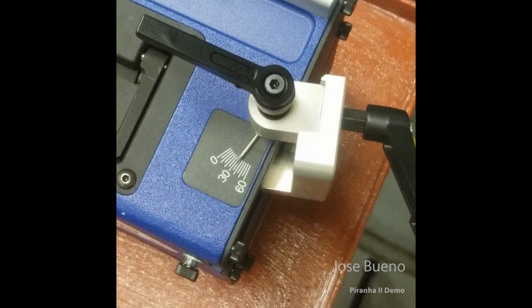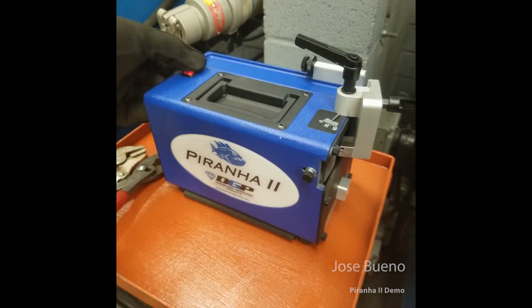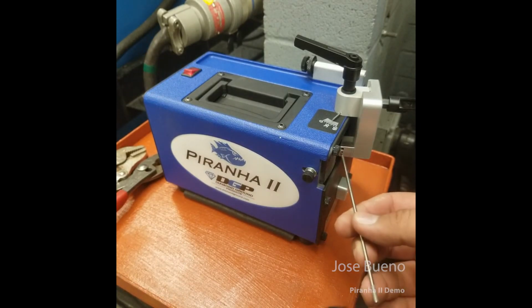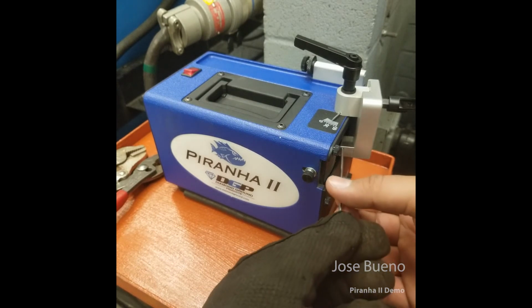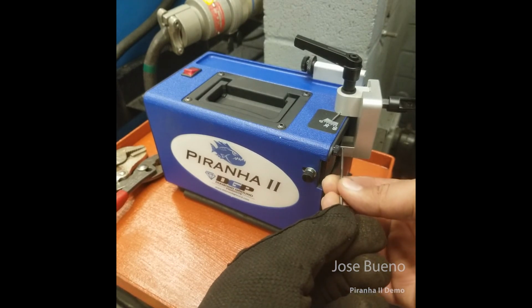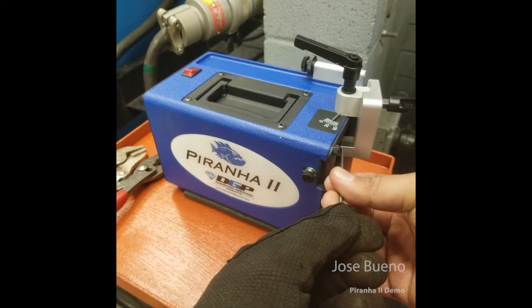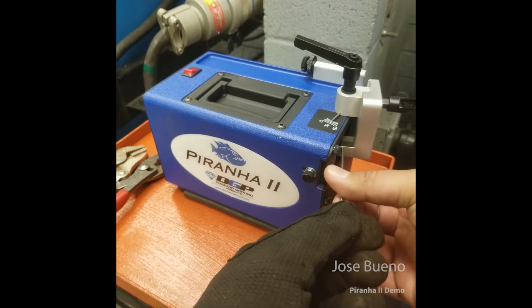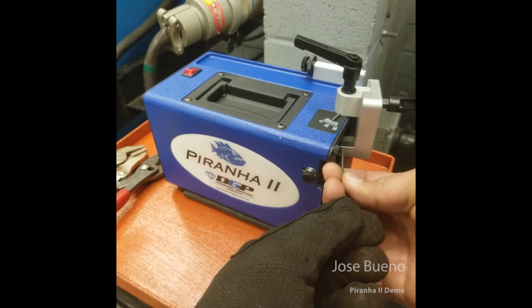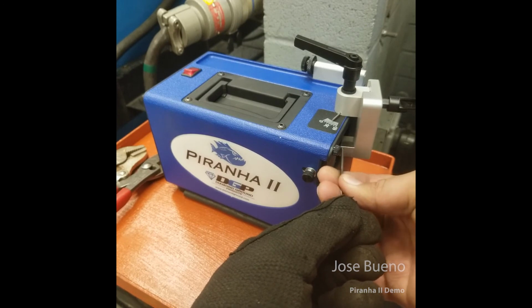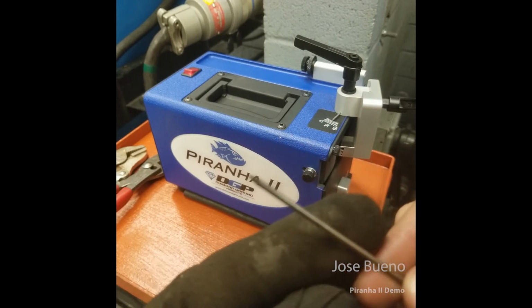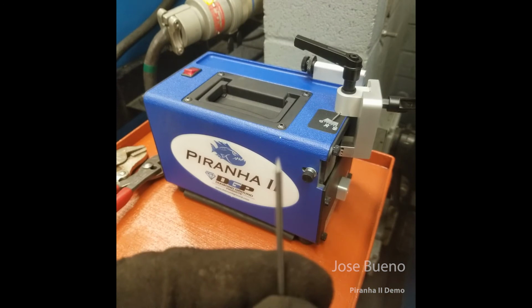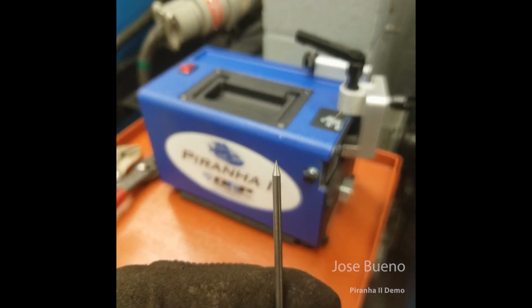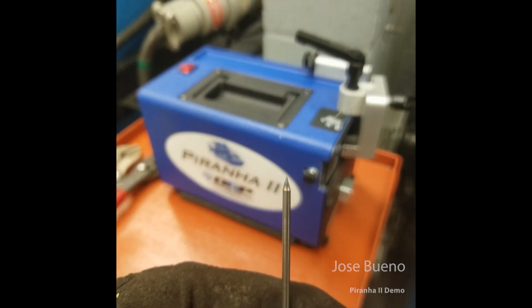And when you're ready to grind, just go ahead and switch it on. Allow it a couple seconds to reach its operational speed, and then slide that tungsten into the guide. Be careful not to apply a lot of pressure to the tungsten electrode, because doing so is going to produce an uneven wear on the grinding disc, and we don't want to wear it out before it's actually supposed to wear out. We want to make sure that these discs last us a long time.